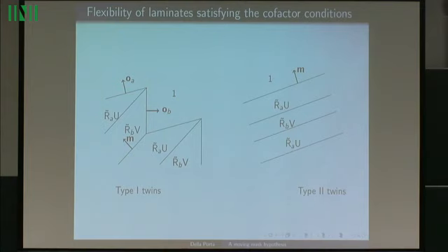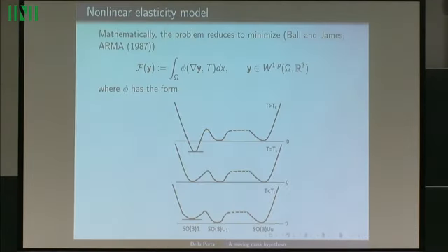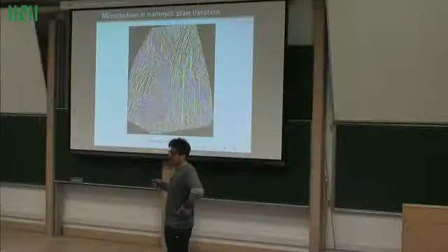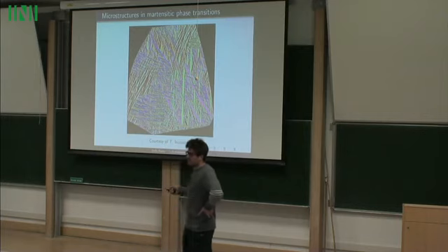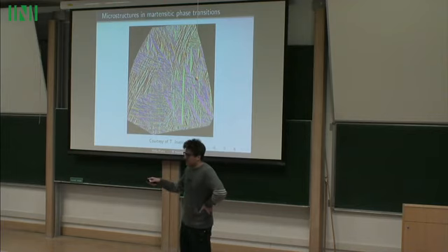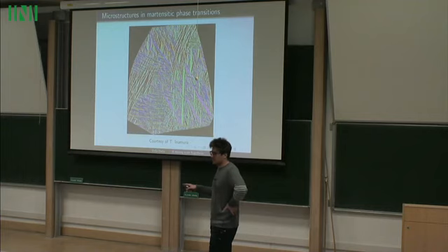Why did you say in the Inamura picture that the ideal microstructure was not theoretically possible? I didn't understand. I've done some computation, and I tried to see whether I was able to match these identity boundary conditions by just using 12 deformation gradients of the form identity plus a tensor n. And this turns out not to be possible. If you take the quasi-convex hull of the set generated by these 12 matrices, it does not contain the identity.